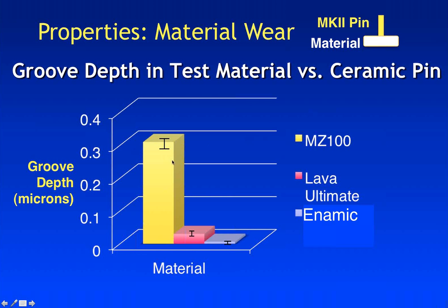So in this test, we were looking at the groove depth that was created in MZ100 and Lava Ultimate and Enamic. This is a higher groove depth. The higher the groove depth, the more it means that the material itself is wearing away. So if we look at the material wear itself, the MZ100 is very high. The Lava Ultimate, yes, there was a significant improvement, so 3M did make an improvement in the Lava Ultimate. However, the Enamic is statistically and significantly better than the Lava Ultimate or the MZ100.